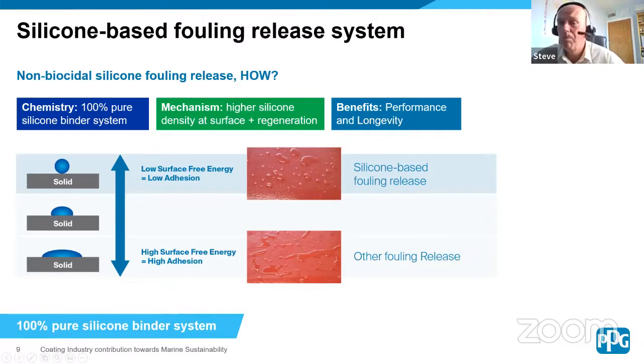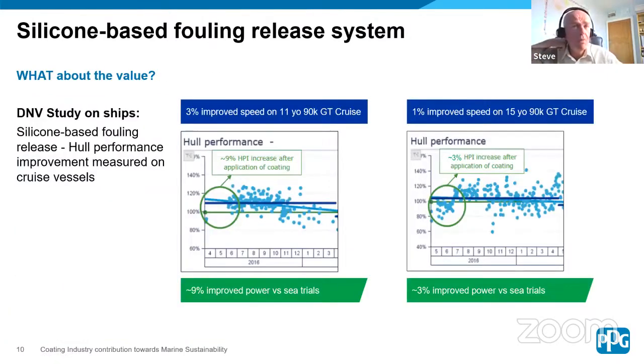What does this all mean in terms of performance? Well, I'm sure you're familiar with these types of graphs where we're looking at hull performance over a period of time. This is an interesting one in that these are two similar size cruise liners, 11 and 15 years old. And you can see the respective power improvements both vessels experienced having had a fouling release system applied. In fact, what's really quite surprising is DNV, who conducted this analysis, was surprised to see a positive effect, a speed improvement benefit over the baseline. They'd never seen that before with conventional coatings technology.